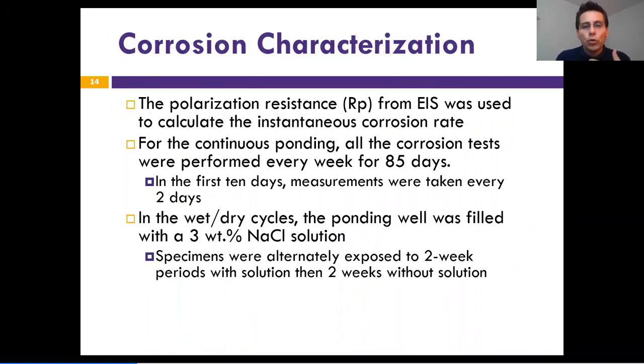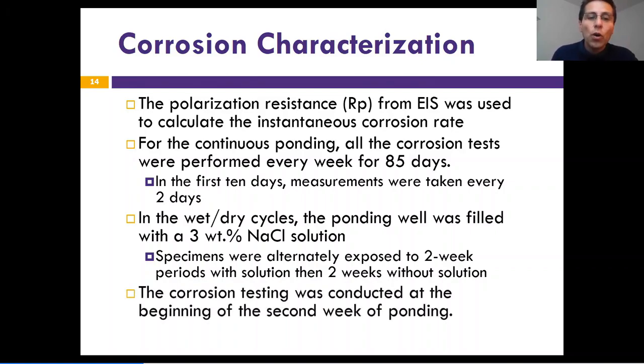For the corrosion characterization, we also did the polarization resistance. And this is very important. Most of the time in corrosion, amazingly, it takes several days to start to see corrosion in concrete. So what we did is accelerated testing, which means that we reduce the time of the characterization. We did wet-dry cycles. We do this because we change the oxygen concentration in the environment to induce corrosion. In this way, we accelerate and take less time to see the effect of the microcapsules in stage one. So the corrosion testing was with this solution, which is very, very corrosive, and also, again, the accelerated testing.